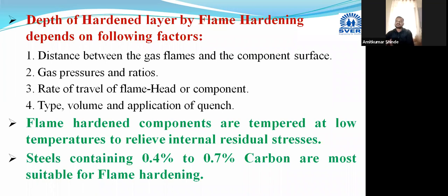And another important aspect is the quenching medium we are using: its type, its volume, and the application method, whether we are spraying it or using the immersion technique. Depending on this, we will get the case depth of the hardened layer. The case depth of the surface hardening depends on these four parameters.